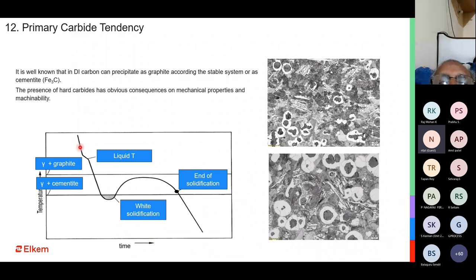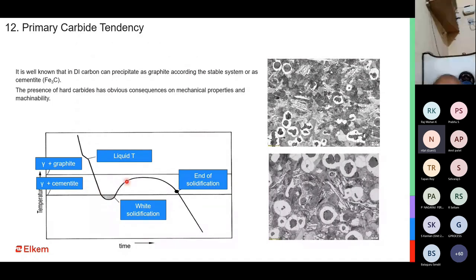So if you look at it, this is a temperature versus time thermal graph. When solidification happens, you want the carbon to start precipitating at a higher temperature. That is the eutectic temperature. If the carbon does not precipitate at a higher temperature, it goes much lower, below the white line, and that is where you have carbides or cementite precipitating. So some of you who are familiar with thermal analysis must have seen that we always insist on a higher lower eutectic temperature. Because if the lower eutectic temperature is high, it means you do not cross this white line, thereby you do not form primary cementites or primary carbides. You actually form graphites and then go towards the end of solidification.